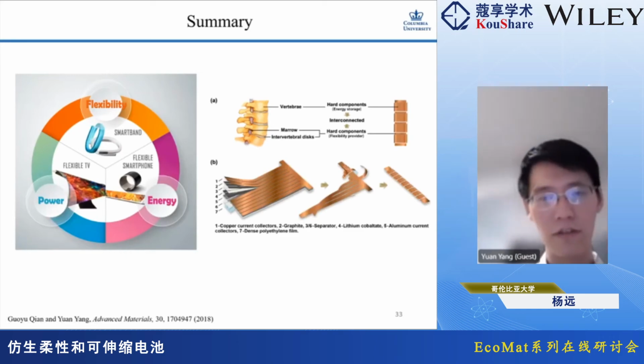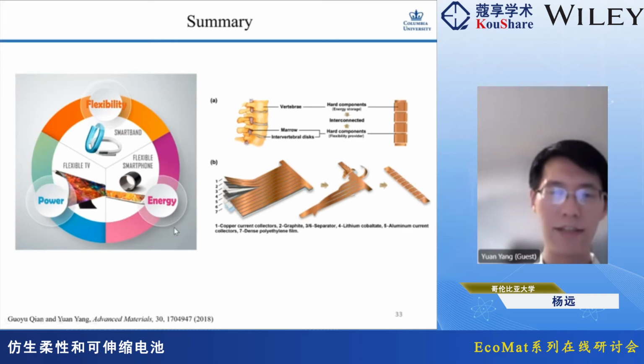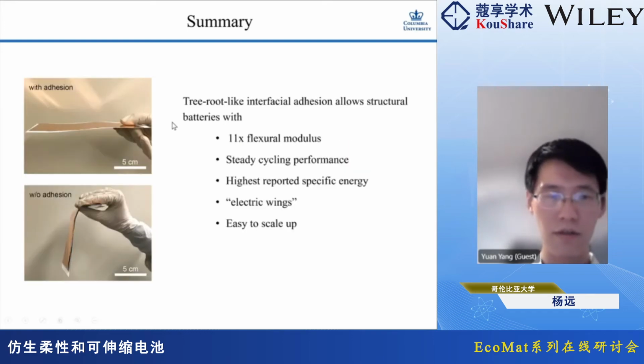Okay, to summarize my talk, in the first part I discussed the flexible battery, and it's important to have flexibility, stable power output, and high energy density together. And we demonstrated this spine-like structure, which has the potential to achieve the three points simultaneously. On the other side, it's also attractive to make batteries very rigid, with lots of applications, not only wearable devices but also vehicles and airplanes. And with simply engineered strong adhesion at the interface between different layers in a battery, we can enhance the flexural modulus of a battery by over 10 times and have steady battery performance. And I think this is one of the highest reported specific energies in structural batteries. And the process is also easy to scale up.